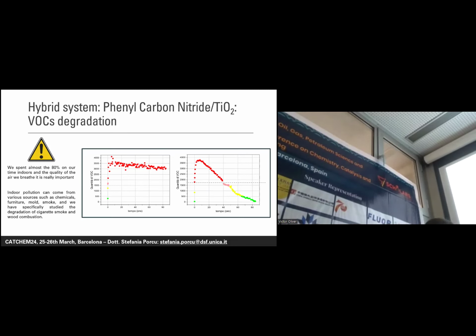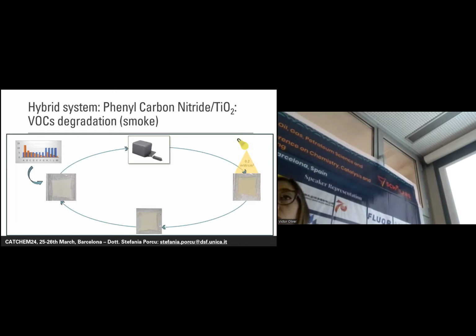So what we observed was that in the second box, in which the photocatalyst was present, we observed a decrease of the pollutants during the time, while where the photocatalyst was not present, the amount of the pollutants remained the same for all the time of the experiment. So we decided to go deeper with this study, focusing in particular on smoke indoor pollution. So what we did was to prepare films of our materials, and using a handmade smoke chamber, we smoked the surface of this film.